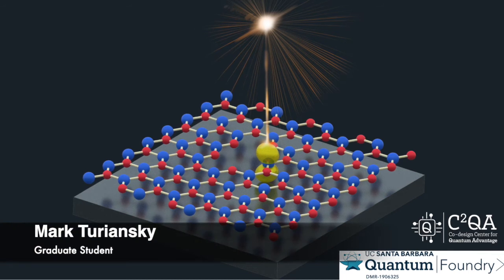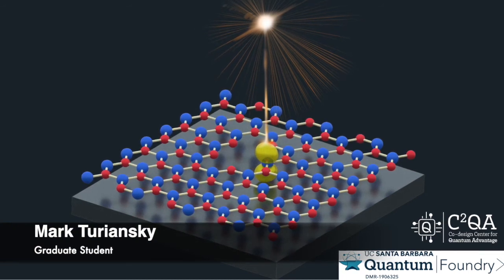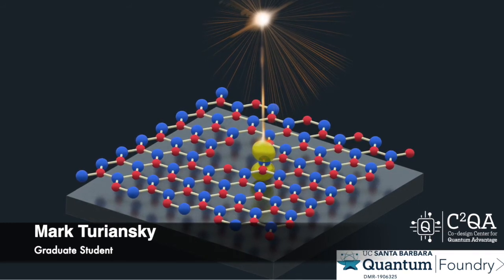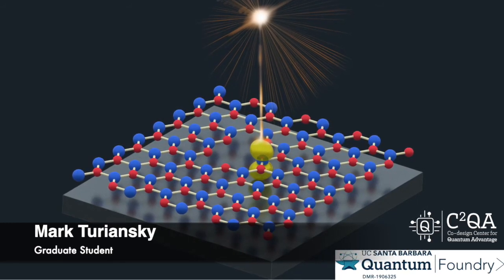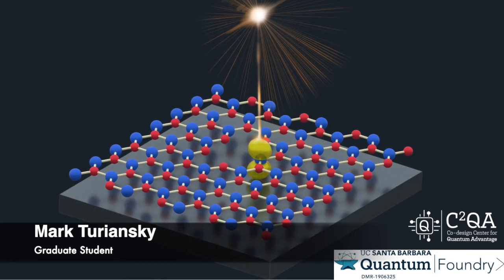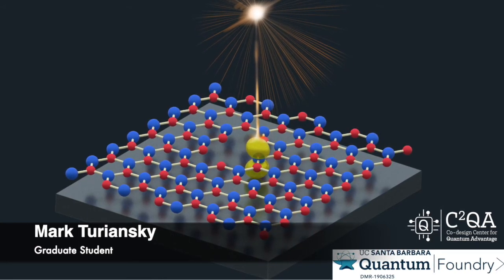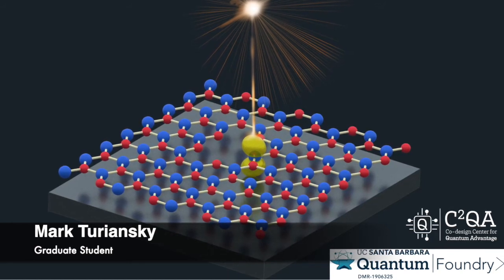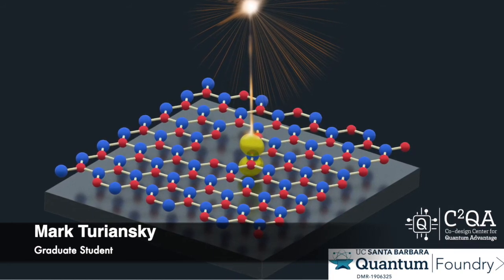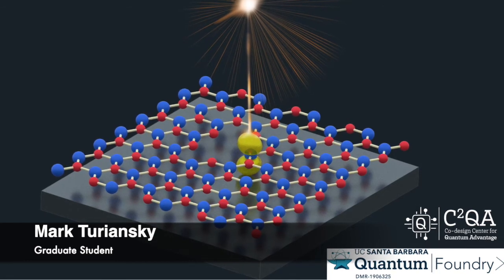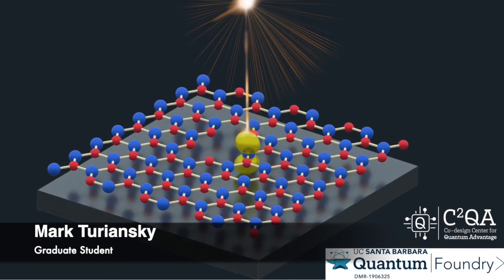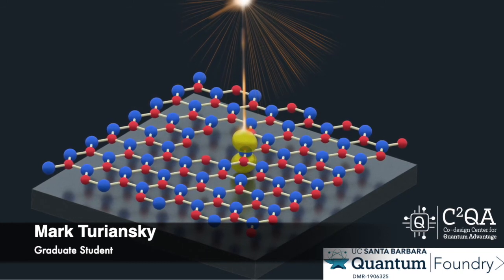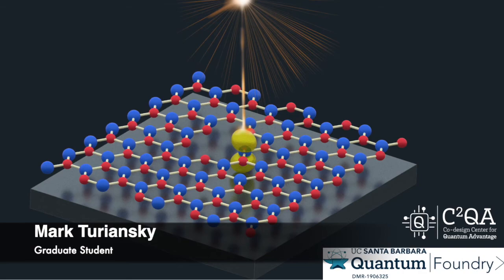We also study materials for applications in quantum information science with an emphasis on quantum defects. Specifically, we use computational methods to identify and characterize novel defects that are promising for quantum computation, quantum communication, and quantum metrology. For example, we have identified dangling bonds and the carbon dimer as the defects responsible for the observed single photon emission in hexagonal boron nitride. We also are actively engaged in developing the methods necessary for a full characterization of quantum defects from first principles.